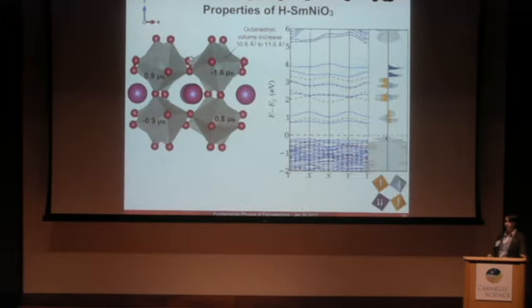So as before, when we added an electron, we see that the added hydrogen provides this electron to the samarium nickelate. Now, instead of just a general positive background charge, we have pretty much a proton sitting right here in our structure. So the magnetic moment of this nickel is again doubled. We see a similar volume increase. However, before, the volume increase was quite uniform. There was nothing breaking the symmetry and distorting the octahedra. But I'll touch on this in a second.